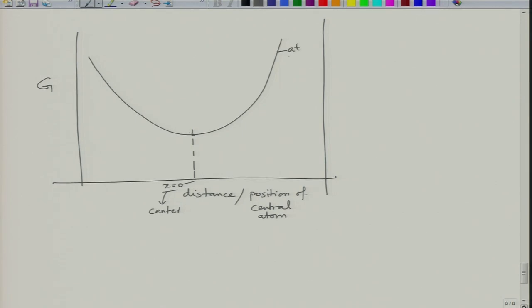However, this is at T greater than TC. When the temperature changes, the free energy shows a double well kind of structure. So there are two minimum positions. These correspond to plus x or minus x. They correspond to minus PR or plus PR. So these are both equivalent energy positions. So this is the maxima now. At x equal to 0, you can see there is a local maxima, which means x equal to 0 is not a stable position. The atom cannot sit here. The atom has to fall either here or here. Okay. So depending upon the local perturbations, it will fall into either the right one or the left one.